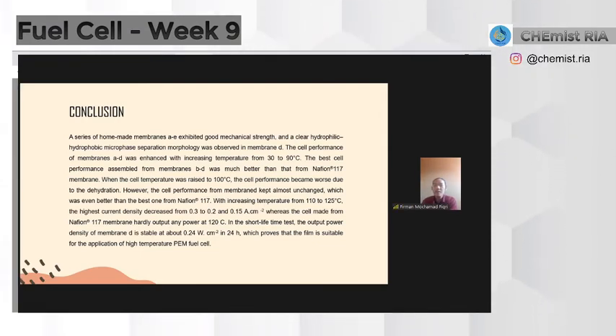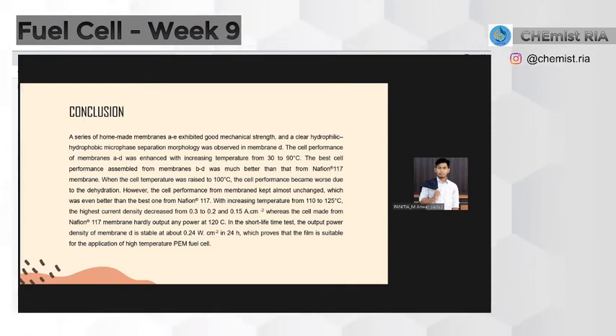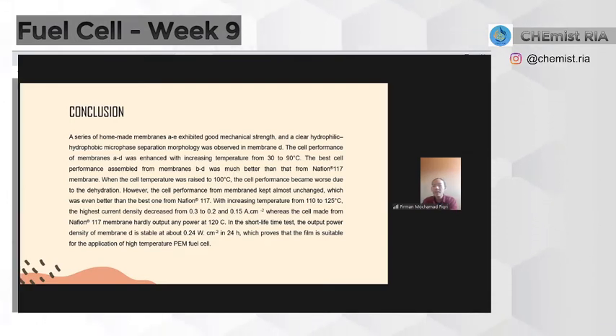With increasing temperature from 110 to 125 degrees Celsius, the peak current density decreased from 0.3 to 0.2 and 0.15, whereas the cell made from Nafion 117 membrane hardly output any power at 120 degrees Celsius. In the short lifetime test, the output power density of membrane D is stable at about 0.24 W in 24 hours, which proves that the film is suitable for the application of high temperature PEMFC.